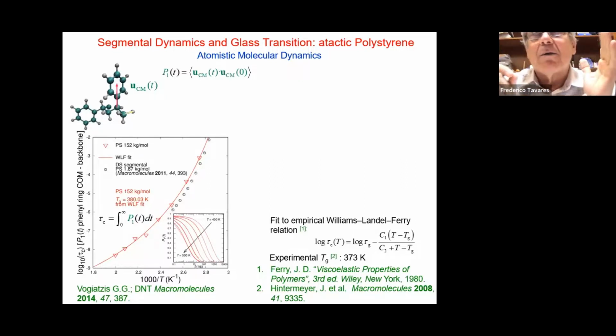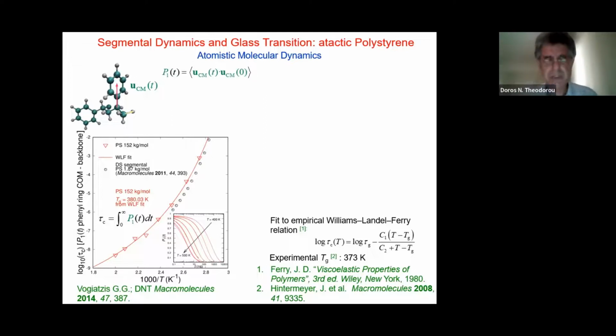But when you do a quench, how will you guarantee, looking at the free energy landscape that you have shown us, a lot of minima? How you get that is exactly the problem. That is exactly the problem, Fred, that if you do a quench, you don't really give the system sufficient time to wander into different minima. So the relaxation is much more incomplete than it would be at a slower rate. If you cool at a slower rate, then of course the system has more time to diffuse out into these other minima. Therefore, it relaxes better.